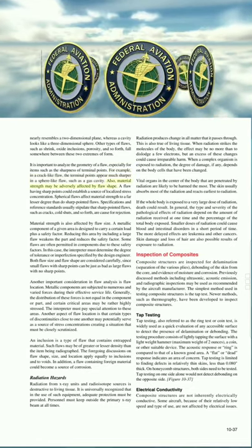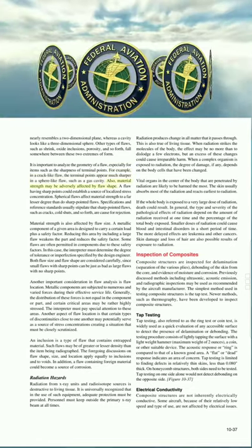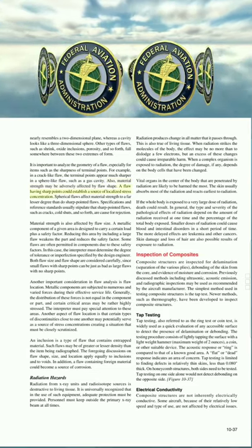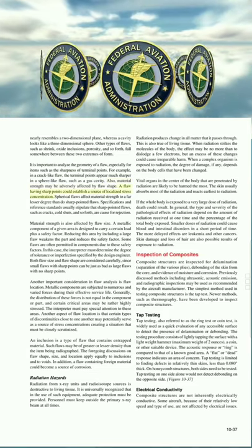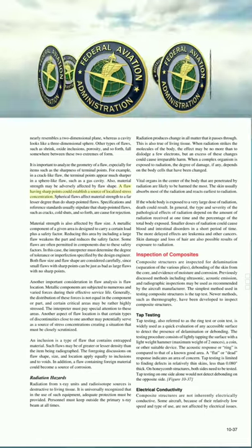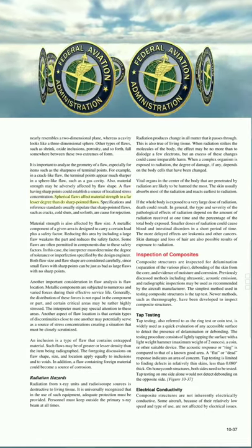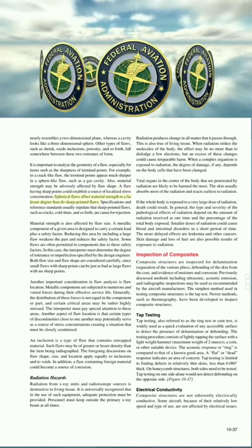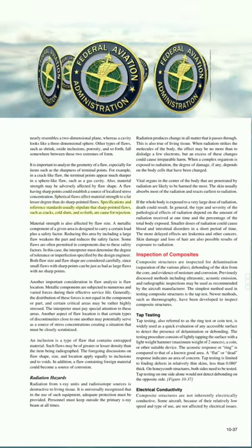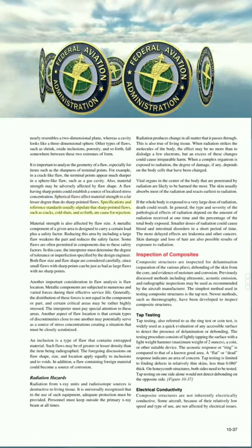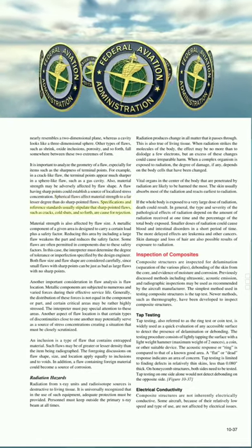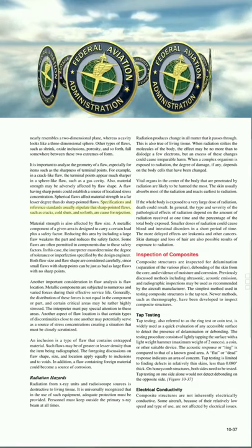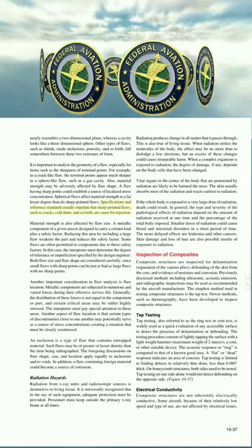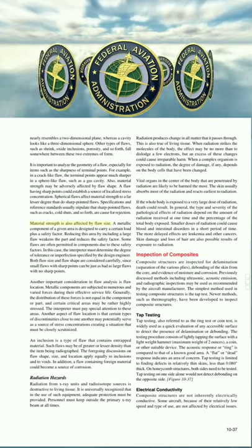Also, material strength may be adversely affected by flaw shape. A flaw having sharp points could establish a source of localized stress concentration. Spherical flaws affect material strength to a far lesser degree than do sharp-pointed flaws. Specifications and reference standards usually stipulate that sharp-pointed flaws, such as cracks, cold shuts, and so forth, are cause for rejection. Material strength is also affected by flaw size.